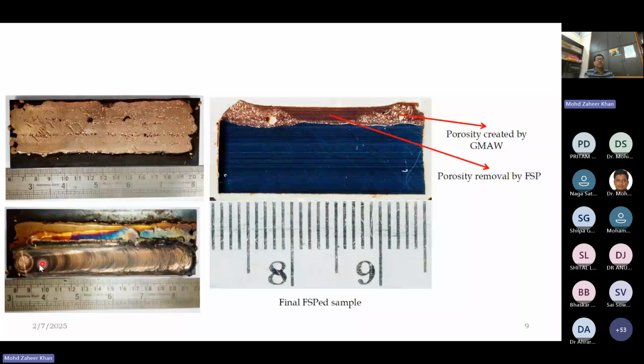It's a very nice and completely filled plate. And most importantly, when we cut the cross section like this and looked at it, in the region where friction stir processing has been carried out on the copper, there was hardly any porosity. So this operation of friction stir processing completely removed the porosity that was caused when gas metal arc welding was carried out. Of course, for comparison purposes, there is a nearby region where only the GMAW process has taken place, and you can see some porosities still present, and many of those porosities are very large in size.